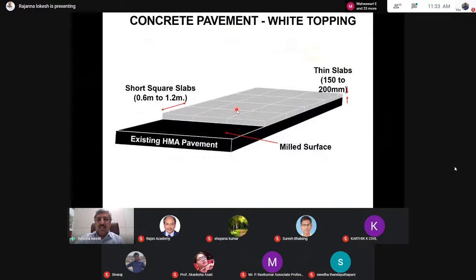This is a photograph showing white topping. White topping can simply be described as a concrete overlay on the existing flexible pavement. Generally the panel size of concrete white topped pavement will vary from 0.6 to 1.2 meters. There will not be any dowel bars, but tie bars are a requirement decided based on the width of the carriageway. Generally, the thickness of the concrete overlay on the existing bituminous surface will vary between 150 mm and 200 mm.